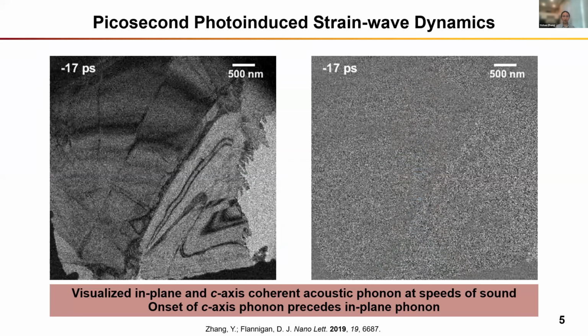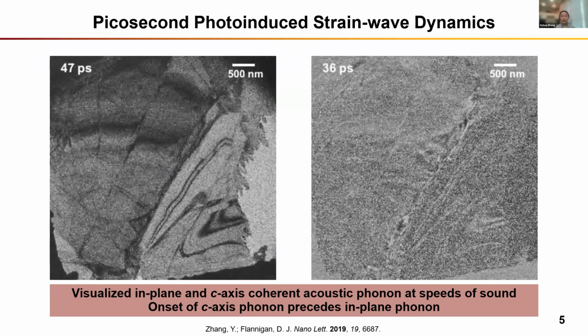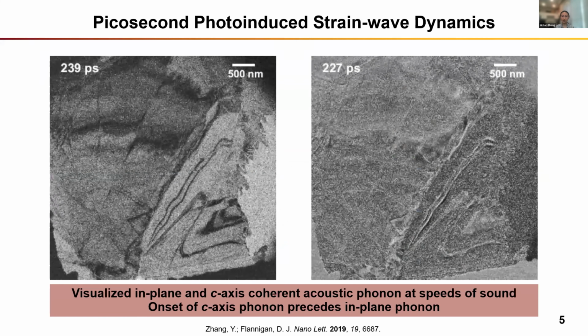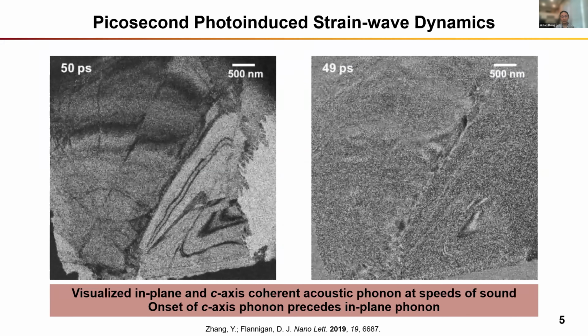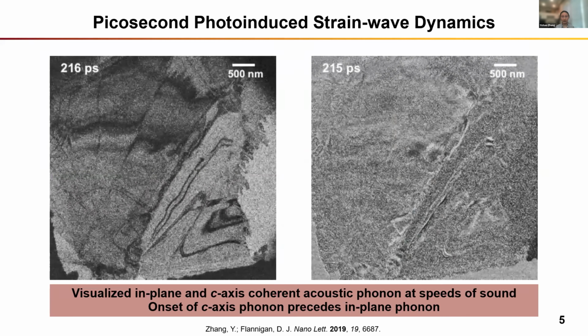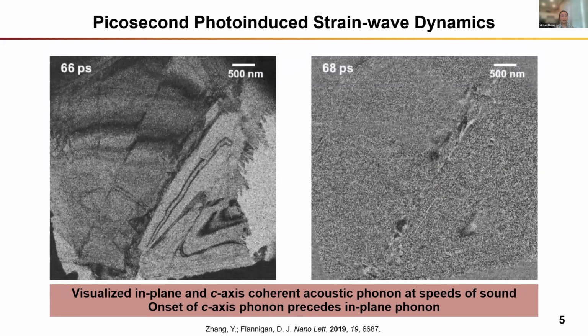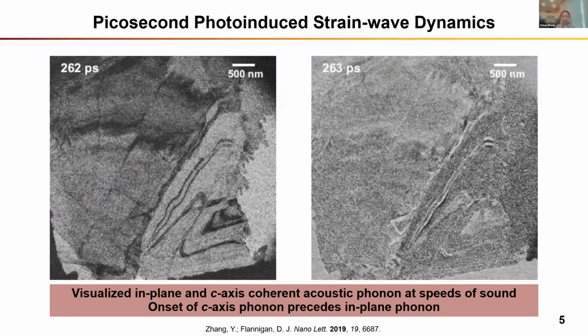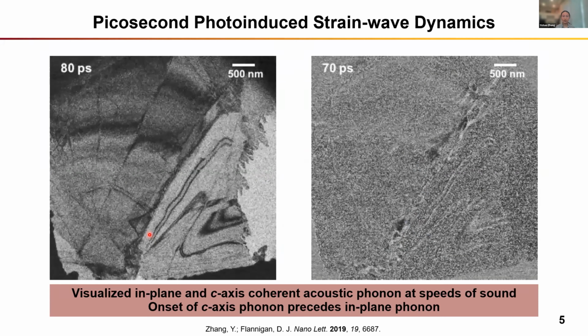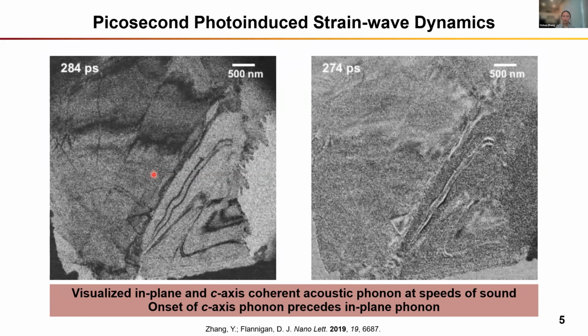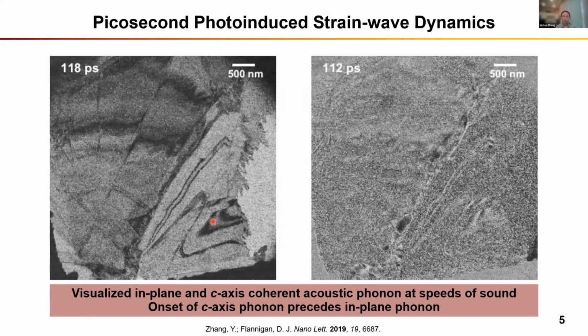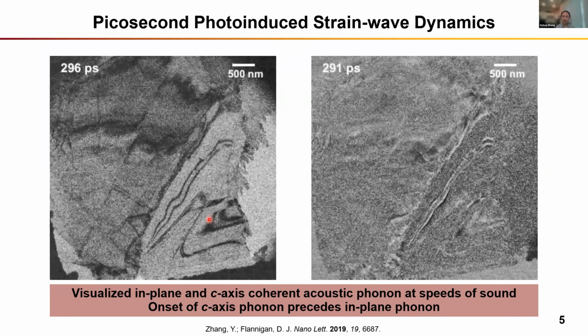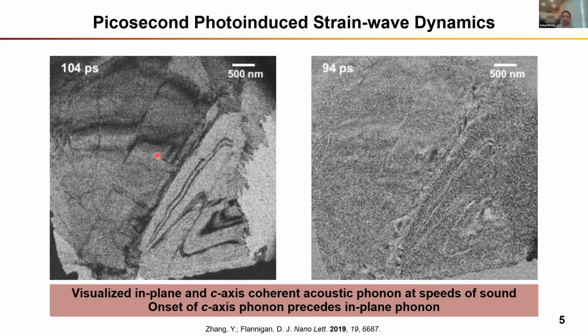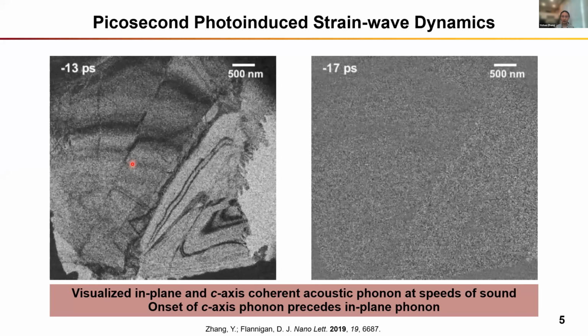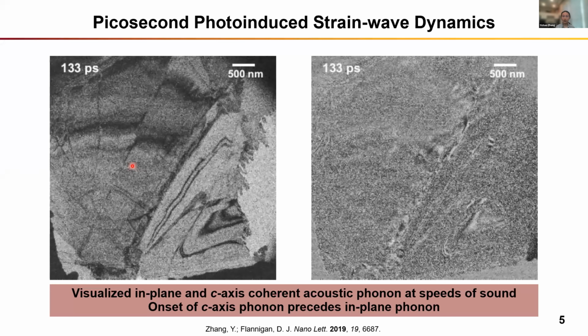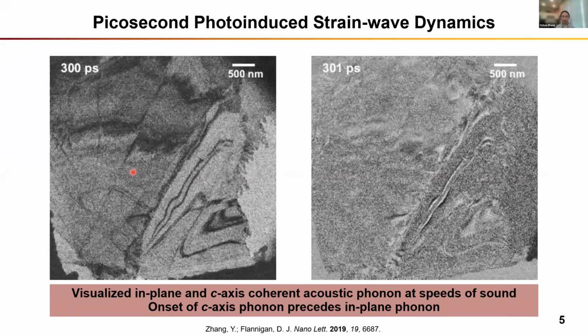Okay, so here's an example of a UEM video. In this experiment, the specimen of interest is an MoS2 flake. MoS2 is a type of transition metal dichalcogenide, and this class of material is best known for its exceptional strain tunability. As you can see, most of the specimen here is approximately along the [001] zone axis, and this thinner, brighter region on the right is tilted at about 40 degrees. And we can see some dark contrast features, and these are diffraction contrast features called bend contours.